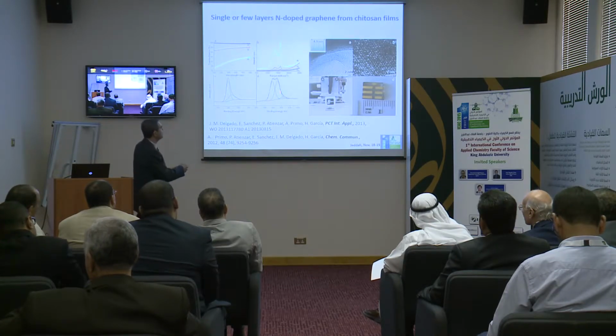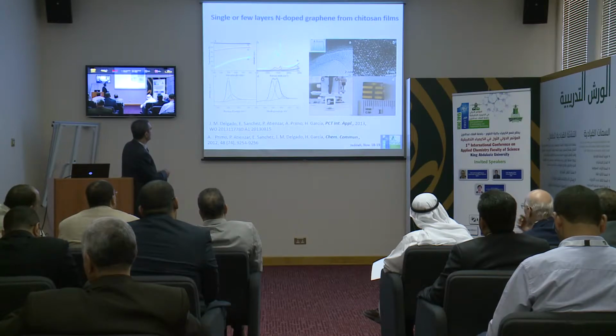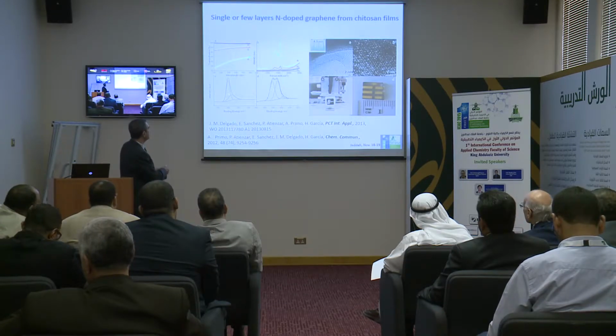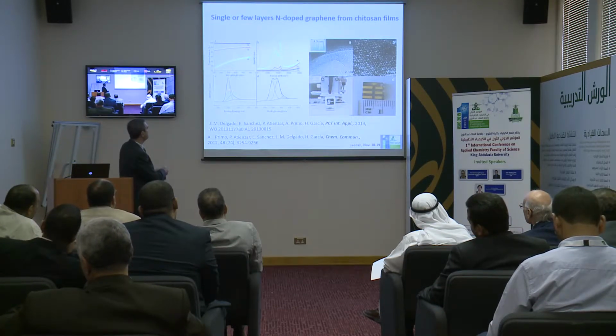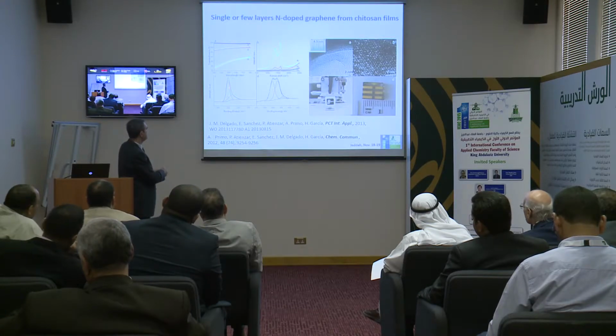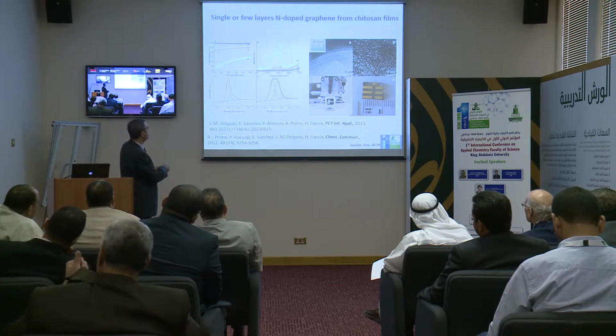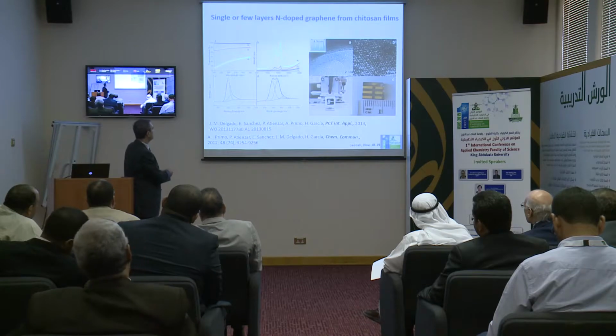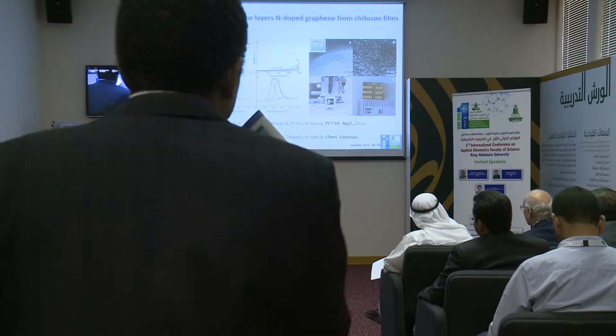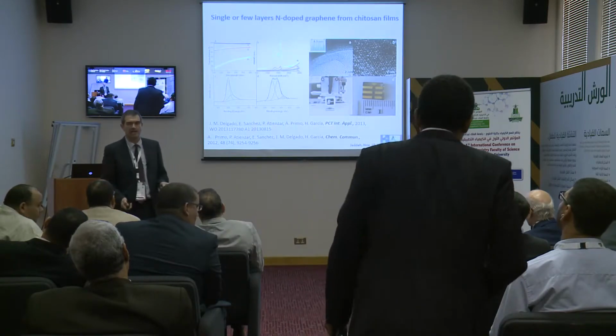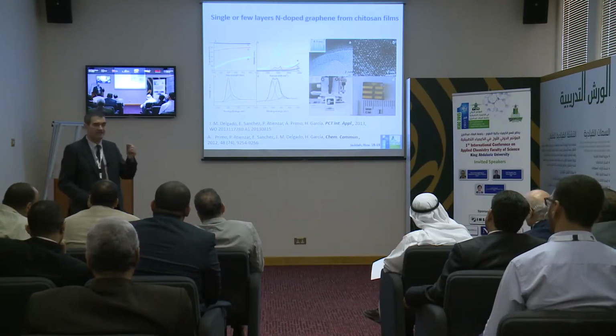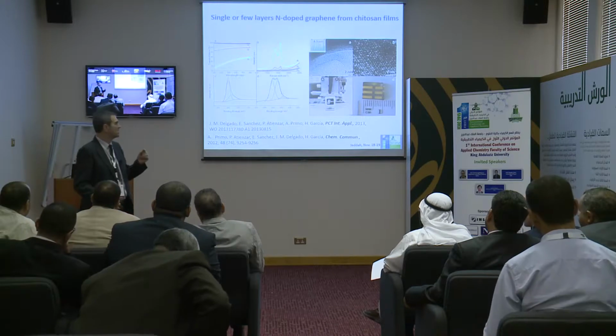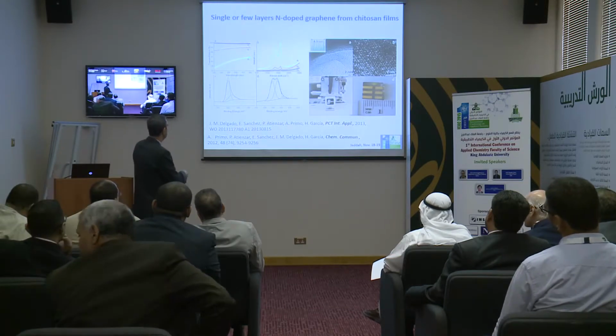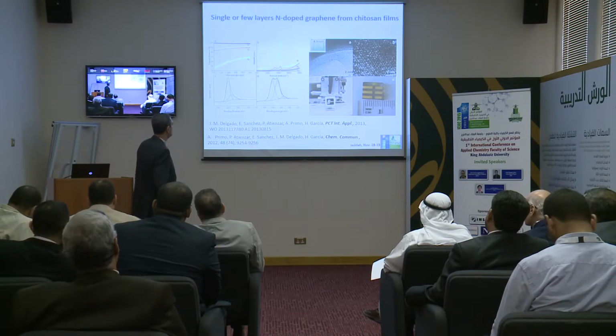XPS is very important in this area, because when you have good graphene, you have only a single peak of carbon in XPS. And here we have 2 peaks. One peak is the carbon on graphene, but we also have another peak that corresponds to the graphene that is bonded to oxygen. And this is very important in catalysis, because we want to have defects, we want to have oxygenated functions, and this indicates that we have some carbons that are bonded to defects.